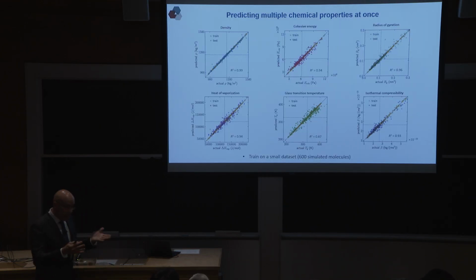All right, and then we see how well these VAEs work for our purposes. So what you see here are predictions compared to actual measurements or simulations for hundreds of molecules, for density, cohesive energy density, which matters for adhesion, glass transition temperatures, etc. And what you see is that in all cases, the predictions are very good. They're very, very reasonable, much better than what we could get with group contribution methods, and comparable to what you can get with simulations. And now the question becomes, this is just prediction, can we actually design new molecules with target properties? Can we invert the process?